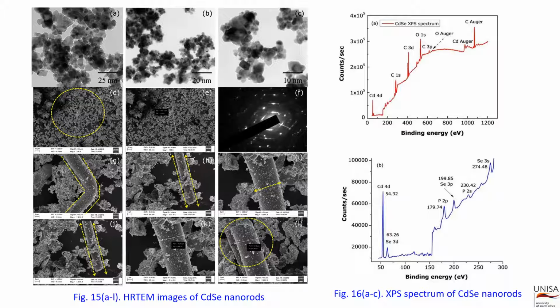To our knowledge, the relative intensity of the cross-sectional surface composition of other elements with lower binding energy peaks are Cd 4d at 54.32 electron volts and selenium 3d at 63.26 electron volts, which is active for the metal selenide, while the other peak, selenium 3p at 199.85 electron volts, has been assigned to a more oxidized state. The P 2p is at 179 and P 2s is at 230.42, with a separation of 1.2 electron volts. The ratio of the intensity of the two components was 2:1.